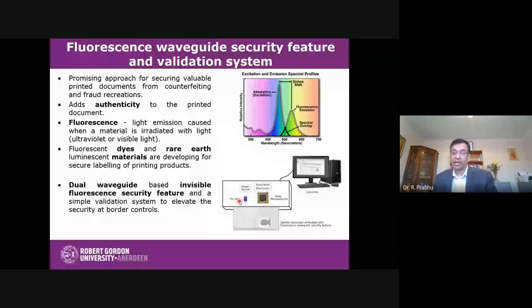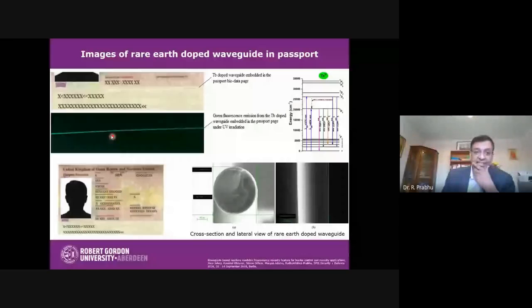So a simple detection system can have a light source and a detector which can be controlled using a PC. And the passport can go through this validation system. So we were trying to integrate an optical fiber inside the data page. This was a rare earth doped fiber. It was a size of probably 25 micron or 30 micron. You can see it's the cross section of the fiber. It's a SEM image, and this is the surface and the cross section.